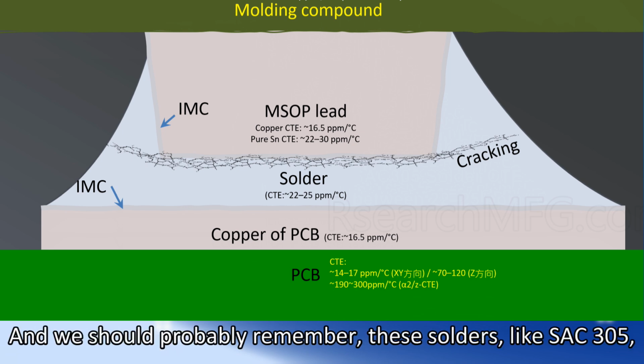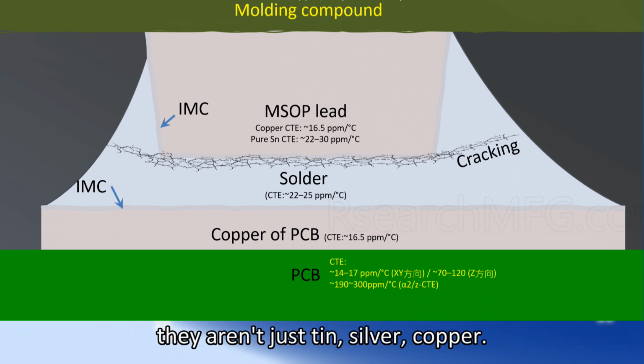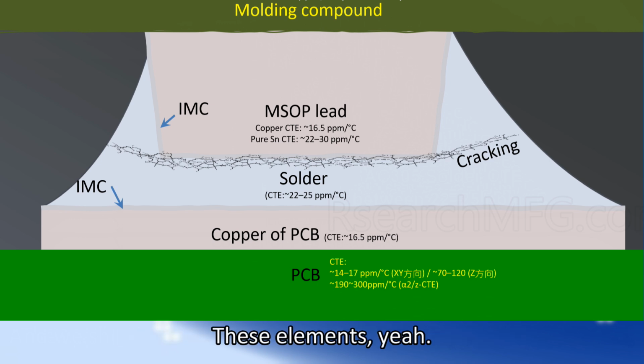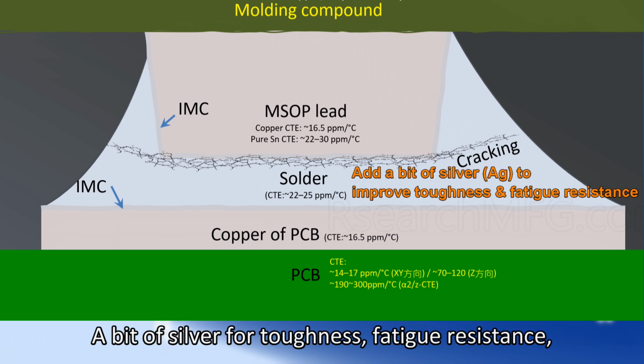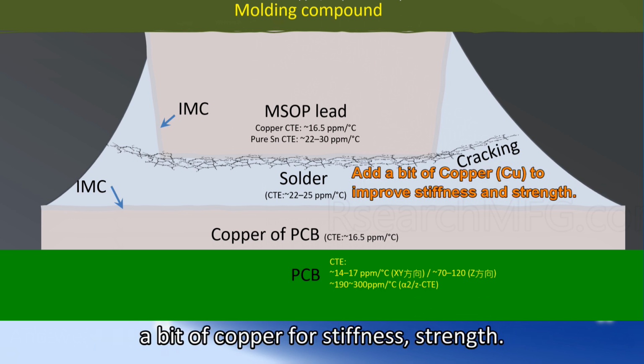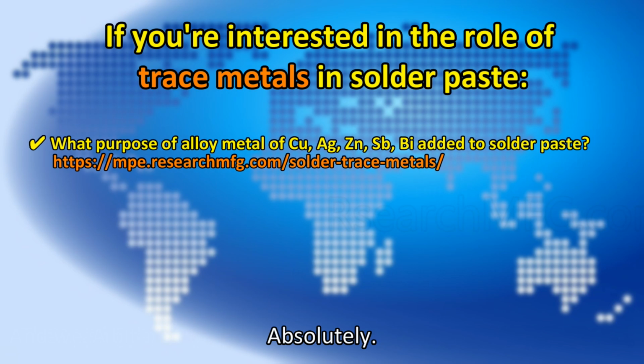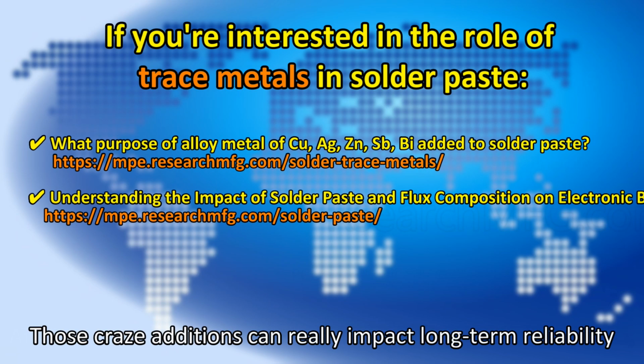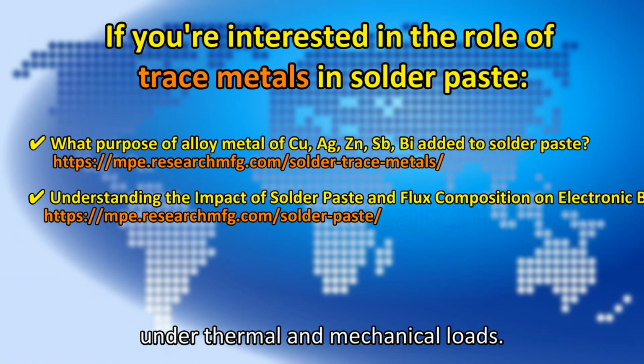Mm-hmm. And we should probably remember these solders, like SAC305, aren't just tin, silver, copper. They have tiny amounts of other stuff, too. Trace elements, yeah. They fine-tune the properties. Yeah, I saw a blog post about it, like a bit of silver for toughness, fatigue resistance, a bit of copper for stiffness, strength. It's a real balancing act. Absolutely. Those trace additions can really impact long-term reliability under thermal and mechanical loads.